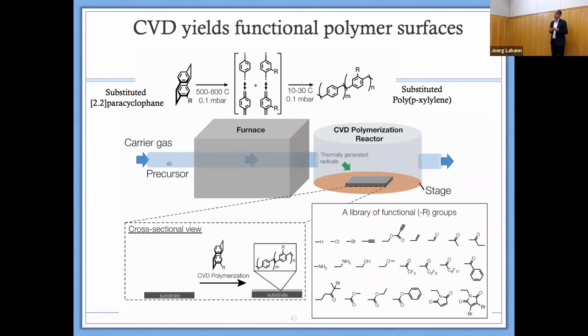We have a little reactor where we take our monomers, we activate them, and we deposit them from the vapor phase onto our substrate. This is a very conformal coating. It doesn't care about the geometry because there's no solvent, there's no bridging effect. So it gives you very homogeneous deposition. And most importantly, the coatings can be exactly controlled. We make them 100 nanometer, 80 nanometer thick. And we can dial in the type of chemistry we need, and that chemistry is picked based on what we want to do with that surface afterwards.